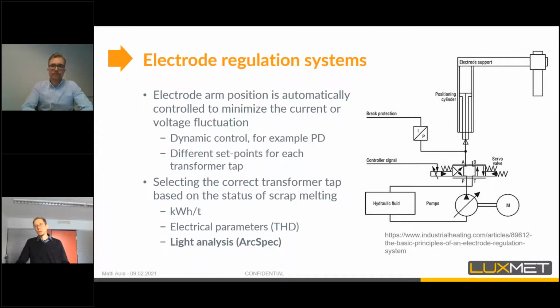Okay, so I have been talking about our technology and the scrap melting in general. There are also a lot of other things that we can control with the process. And one control system which practically every furnace has is the electrode regulation system. In this electrode regulation system, there are two different levels. One is the dynamic fast control level. So the electrode arm position is controlled according to the current and voltage fluctuations. For example, if the scrap falls into the plasma, we want to change the position of the electrode arm so that the arc length stays approximately the same. This kind of control is fast and ongoing, usually done with PD control, with hydraulic actuators.